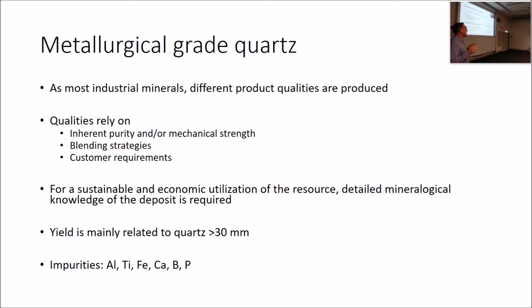Impurities are mainly related to aluminum, titanium, calcium, iron, boron, and phosphorus. Most of the elements that come as impurities can be refined during this metallurgical process, but these elements are hard to refine, so they need to be naturally low in the quartz.